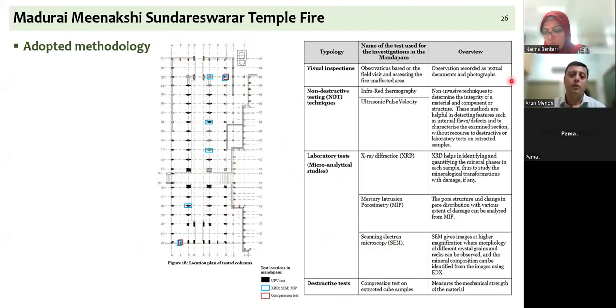Visual inspection was actually complete. The entire structure was documented, but in terms of the non-destructive testing and laboratory testing, this had to be a few samples, but representative enough. So as you can see, the non-destructive testing technique that we finally used was ultrasonic pulse velocity. The infrared thermography, IR thermography, did not really work in this context.